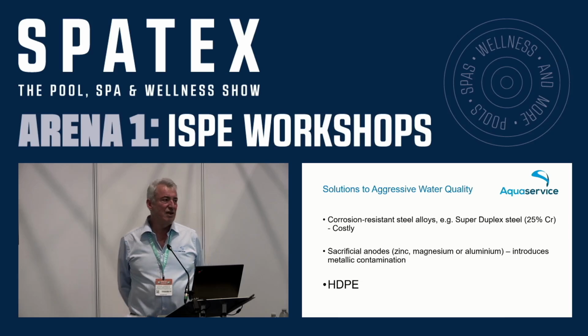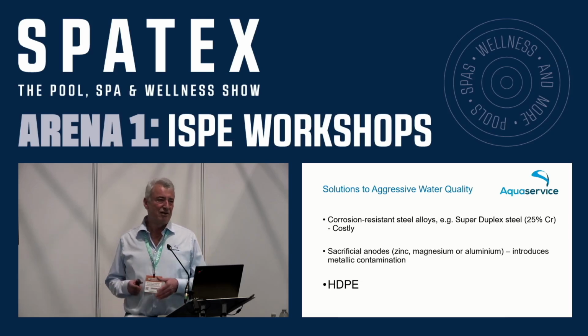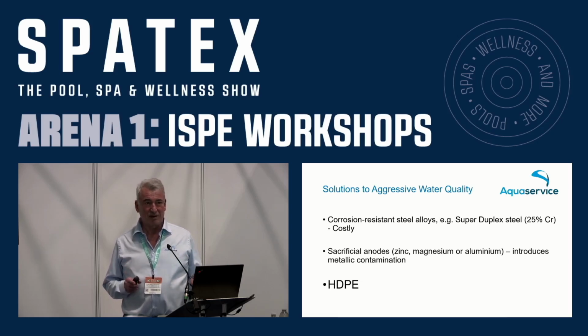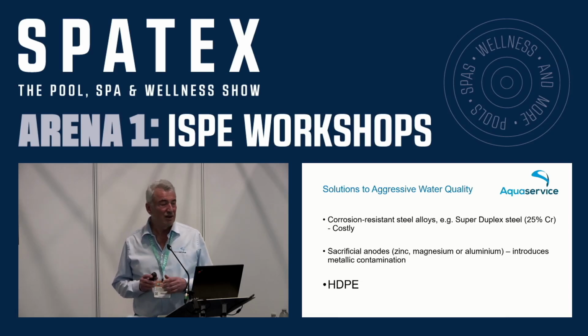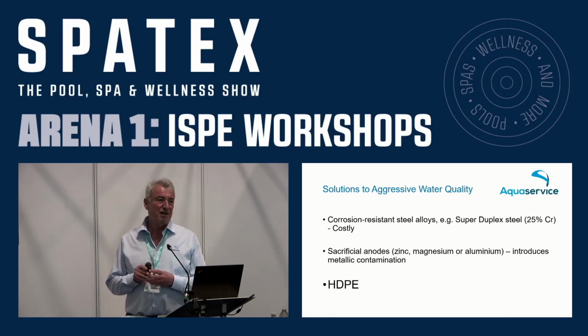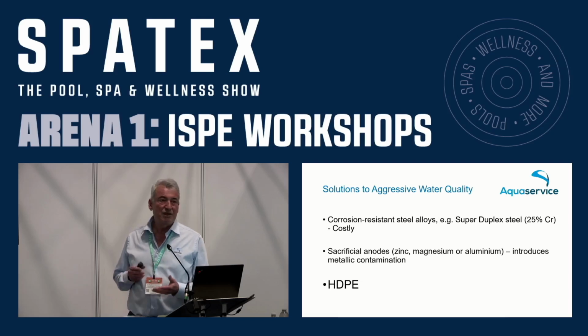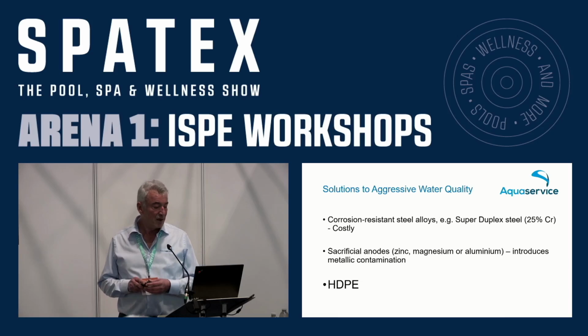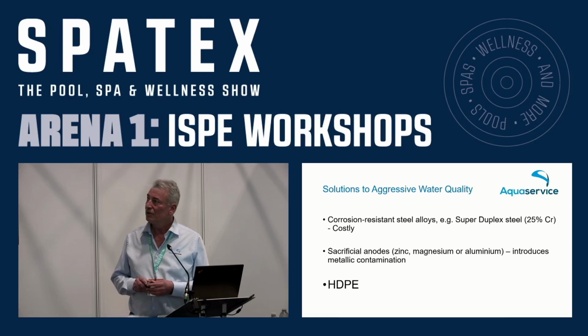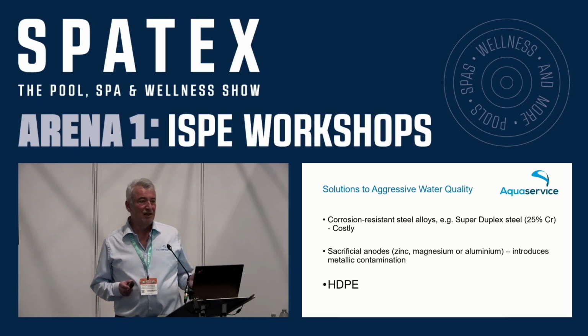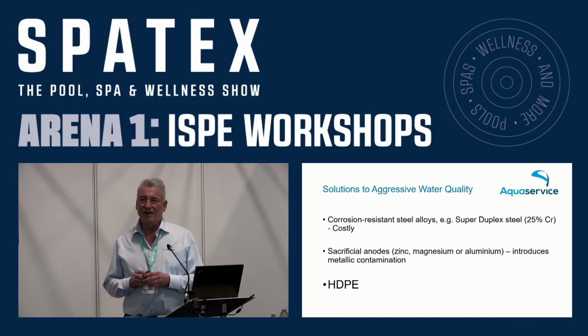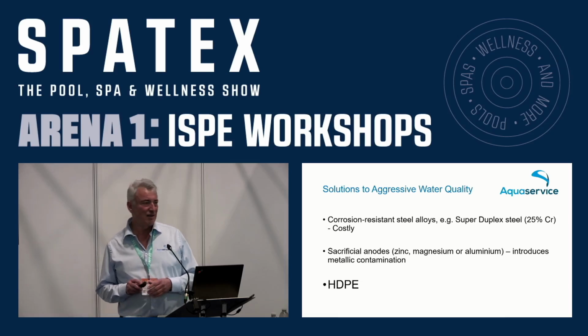Another solution is to use sacrificial anodes. These are anodes that are installed within the UV chamber, and they degrade sacrificially to save the steel body of the chamber. They also work, but they are consumable parts that need changing. But I would say the more significant issue is that they are introducing metallic contamination into the pool. The sort of materials used for these anodes are typically magnesium or aluminium or zinc. And zinc in particular is not a good material to have in pool water. So a third solution is to use a polymer, specifically HDPE, high density polyethylene.